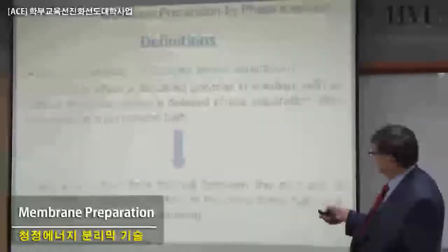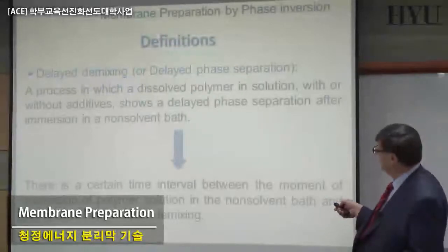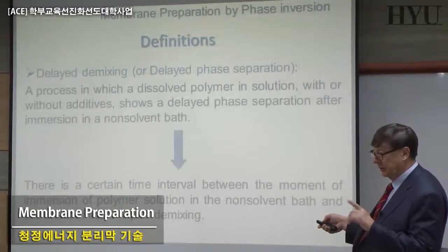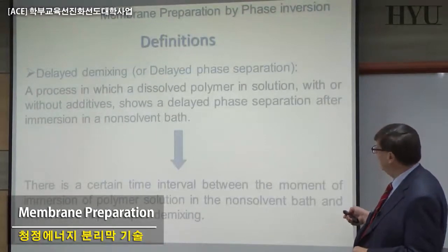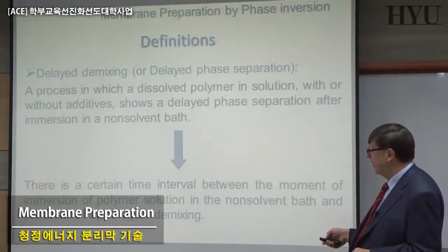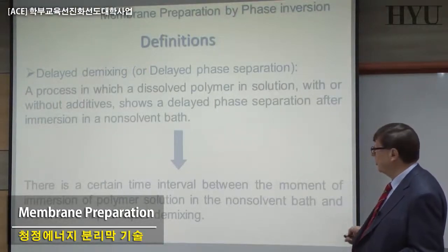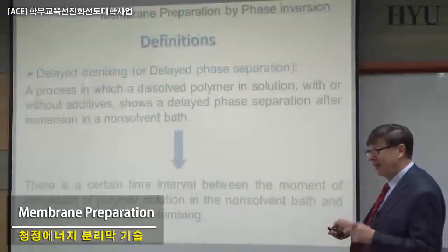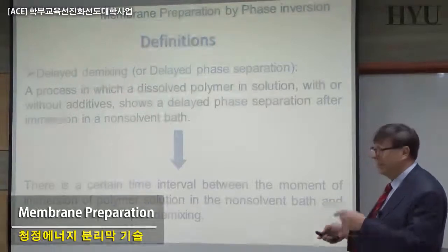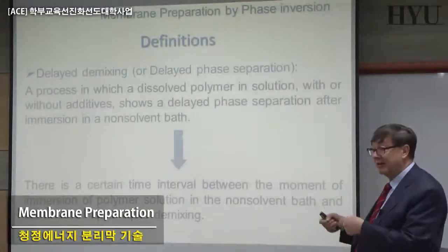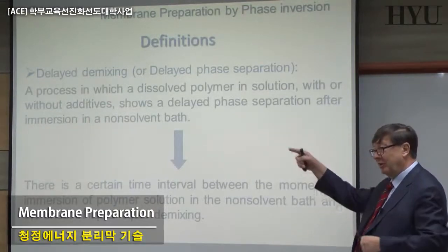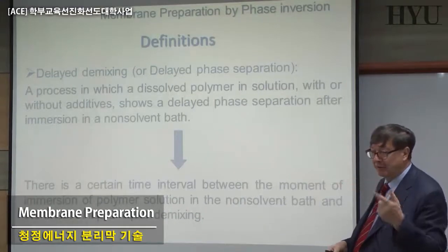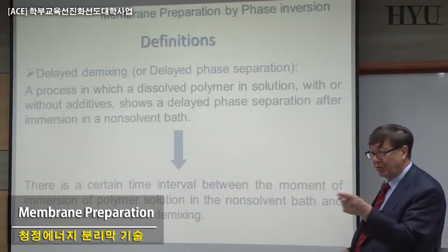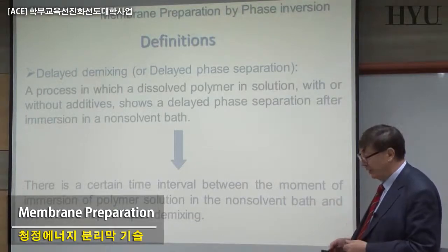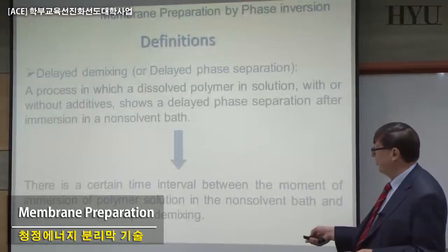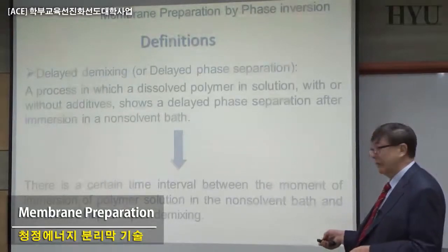Just to show you, remember again, delayed demixing is a process in which a dissolved polymer in solution, with or without additives, shows a delayed phase separation after immersion in a non-solvent bath. Additives can change the scenario completely, by the way. That means there is a certain time interval between the moment of immersion and the onset of liquid-liquid demixing, and this time interval is very important. If you make membranes with this system, check how many seconds, or tenths of a second, you are operating, because this is a parameter. If you change this interval, the air gap, when you spin your membranes, you are changing the final morphology completely. Your colleagues who are spinning can tell you how significant this effect is.